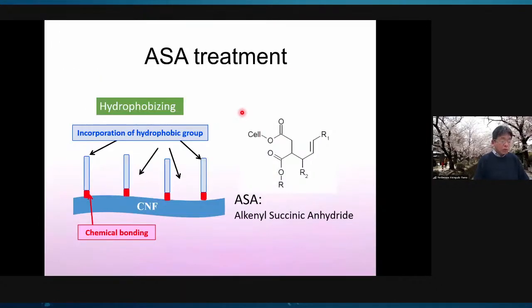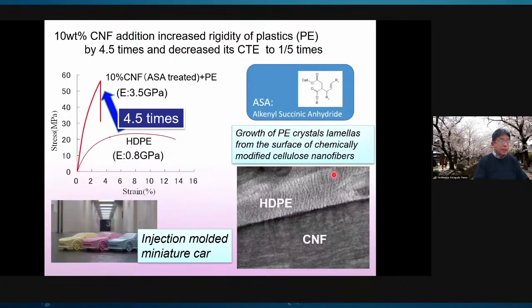On the basis of these results, we focused on ASA treatment. ASA is alkenyl succinic anhydride, and this is its structure. It shows that the 10 weight % CNF addition increases the rigidity of high-density polyethylene by 4.5 times and decreases the thermal expansion to 1/5.